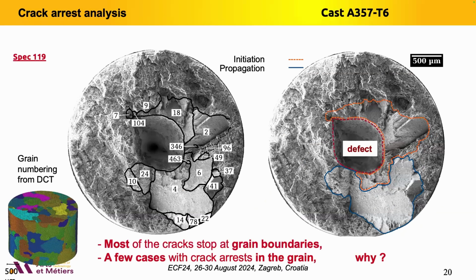By diffraction contrast tomography with the synchrotron X-ray, it's also possible to know the microstructure of the specimen. So the microstructure in terms of the grain orientation and the grain dimension has been obtained here before the cyclic loading. So we have labeled, given a number to each grain. And in this case, we are able to know the interaction between the cracks and the interaction between the slip systems. So in the next slide, I will try to explain why sometimes the crack is stopped on the grain boundary and why sometimes the crack is stopped in the grain.